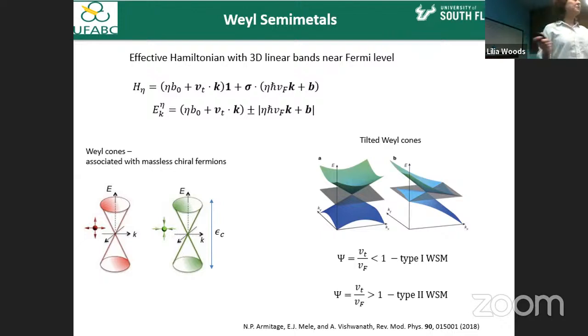And just to say a few words about what a Weyl semi-metal is, well, the Weyl semi-metal is also characterized by Dirac linear band dispersion at 2 cones. But unlike the case of graphene, where the 2 cones are degenerate, in the Weyl semi-metal, which has to be mostly a 3-dimensional material, the cones are separated, so they're non-degenerate. And this non-degeneracy is lifted, so I'll say in a minute what it is. I try to put it here schematically.